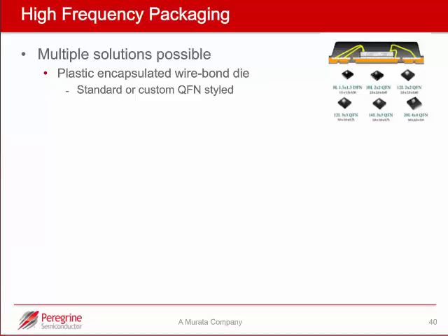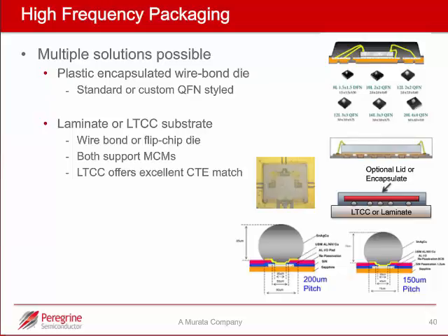Some of the mainstay and ones I prefer are more laminate or LTCC based, and the reason for that is you can customize the interface very specifically for what you're trying to do from an interface perspective. So whether it's wire bond or flip chip, you can customize based on what you're trying to do from an impedance and frequency range perspective. And both of these support multi-chip modules, so it gives you an environment for blending technologies if needed. And I had mentioned earlier that the LTCC offers an excellent CTE match with the sapphire die. So a very clean, mechanical, almost stress-free assembly on that.